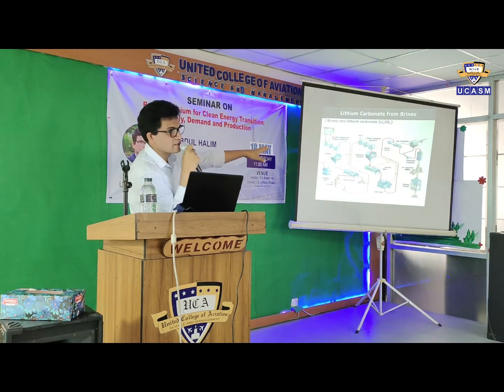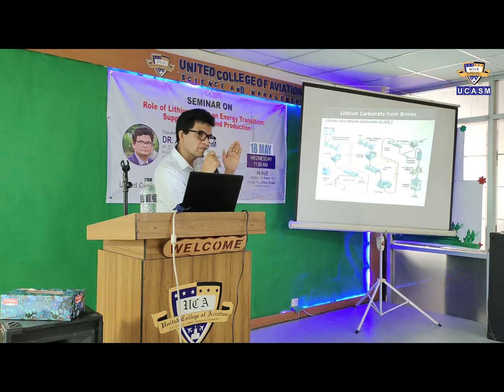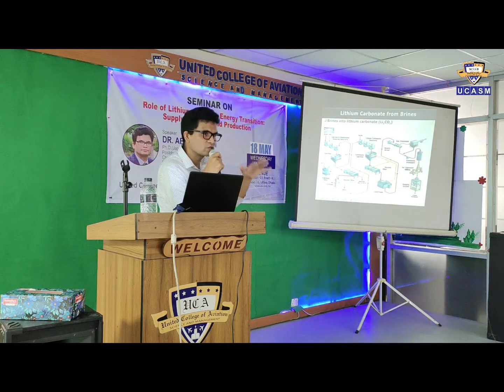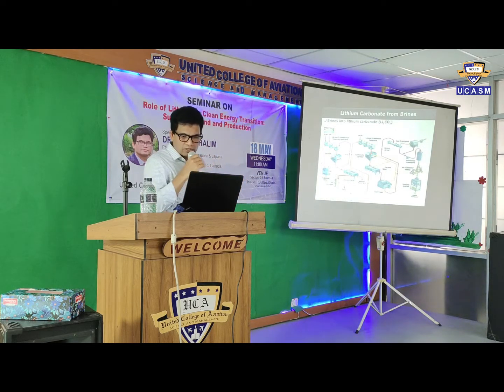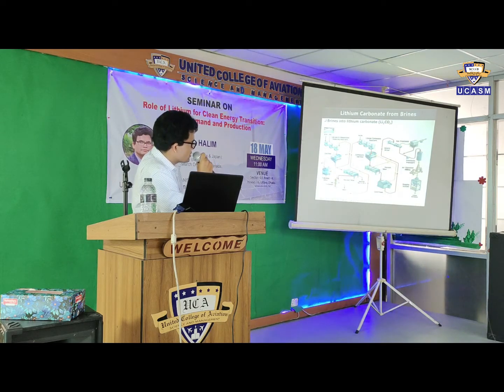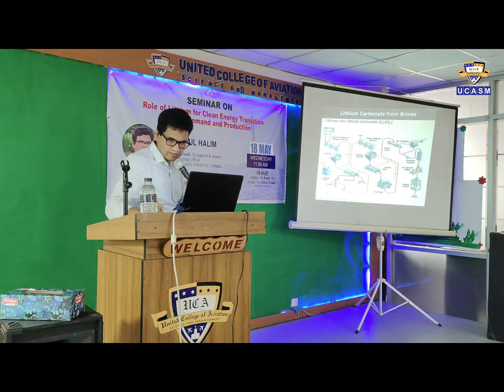Once we get the lithium carbonate as a solid at 95, under certain conditions, meaning if the temperature is increased, the solubility of lithium carbonate decreases. It means most of the lithium carbonate reports in a solid form, not liquid form. Over 95 degrees Celsius, its solubility is almost close to zero. So we get most of the lithium as lithium carbonate. That's why we increase the temperature to about 95 degrees and do the solid-liquid separation, and we have that lithium carbonate solid. We dry it and make lithium carbonate. That is ready to go for the battery making industry.